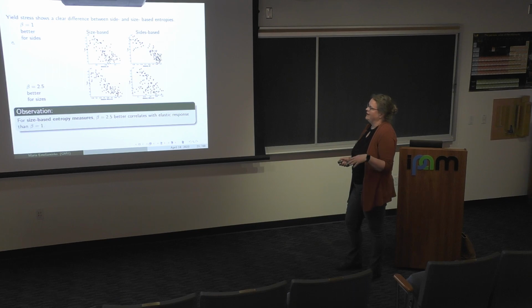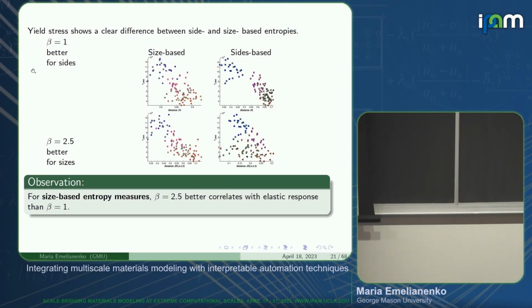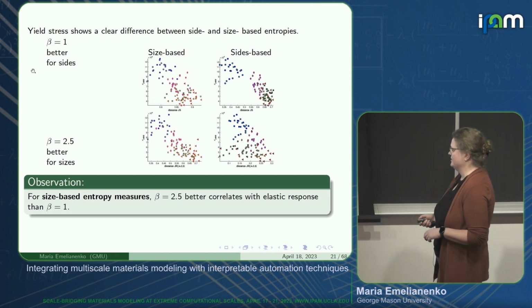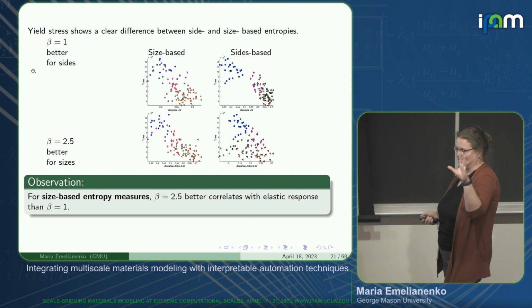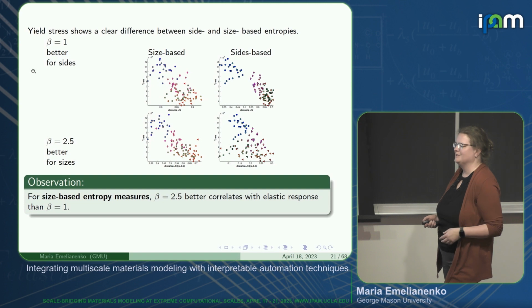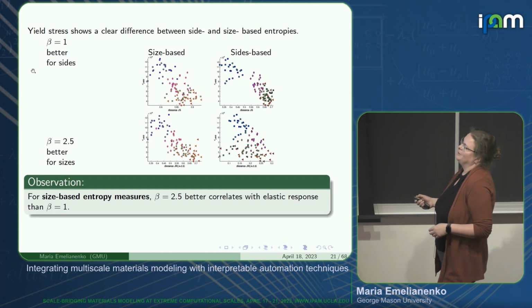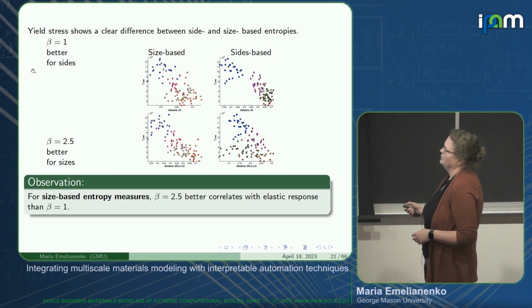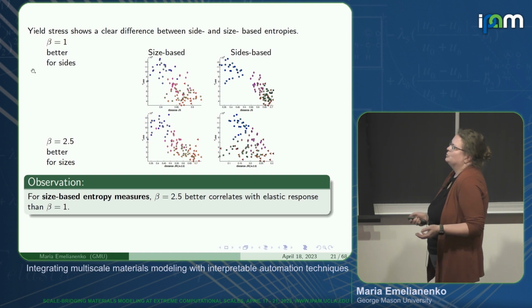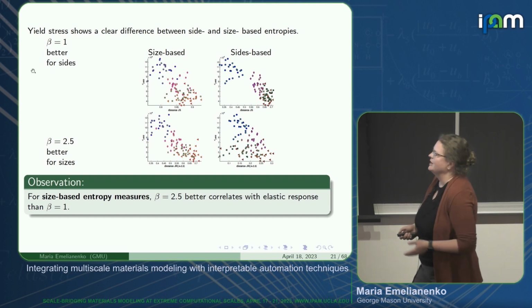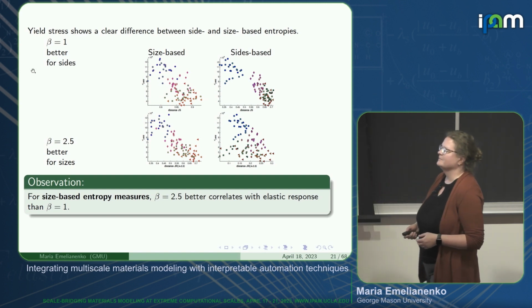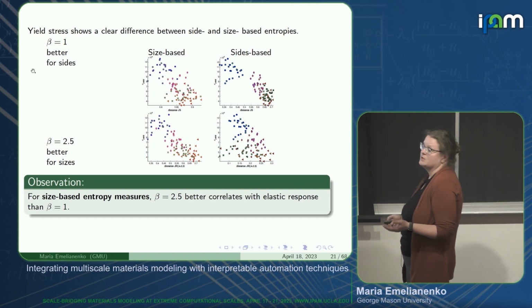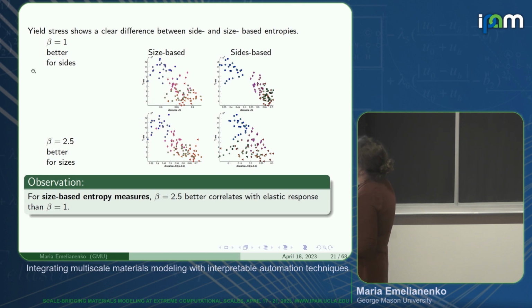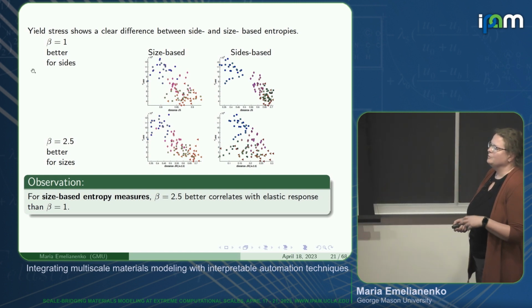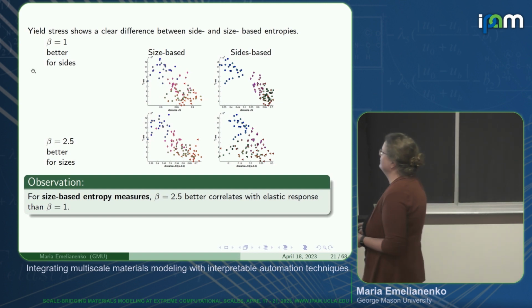The other thing that we did is we looked at the yield stress. What was going on there was less clear, because what we wanted to see is some sort of clear correlation. If we change the entropy, then the response changes accordingly, some sort of correlated behavior. It was better correlated for beta equal to 1 for the sides-based statistic. But when we looked at the sizes of the grains, beta equal to 1 gave us a big mess. When we changed the parameter to 2.5, it allowed us to see those clusters better and to see the correlation better. But this is just empirical evidence. This is not really a theory that can explain it, but it brings us to the realization that there could be a lot of different characterizations of the microstructure. How do we pick one? How do we actually make sense of what's going on? And can we build a theory for it?